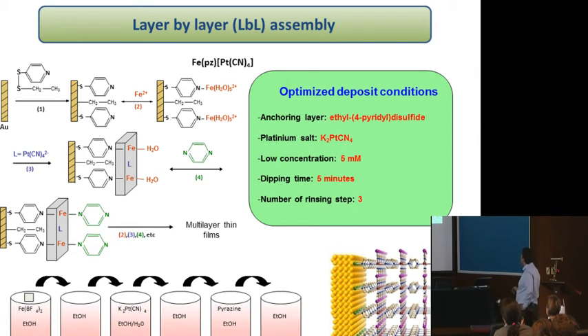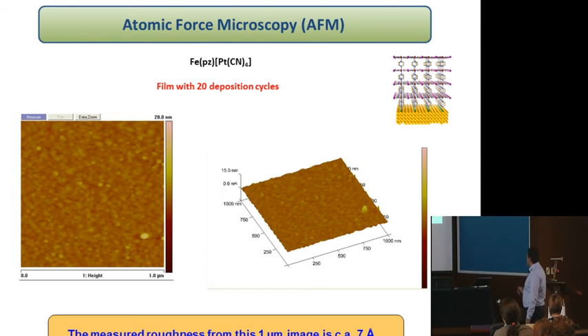Of course, this is not very simple. It seems to be simple here, but we have to control a lot of parameters. So I speak about the anchoring layer, but you have to determine the good sites, the concentrations, also the dipping time, the number of rinsing steps. So it's not very easy. We spent at least 3 years to have very nice films of this kind of compounds. So we already saw this, we can obtain roughness which is less than 1 nanometer on this large area of films.